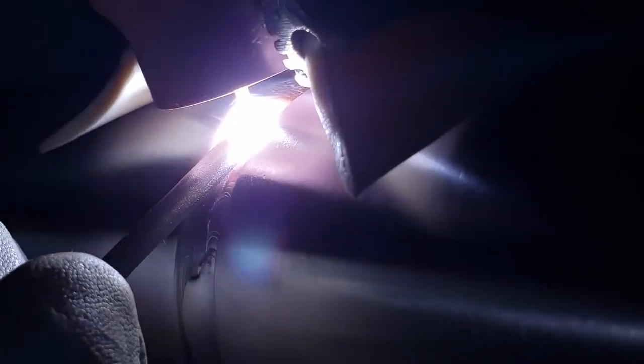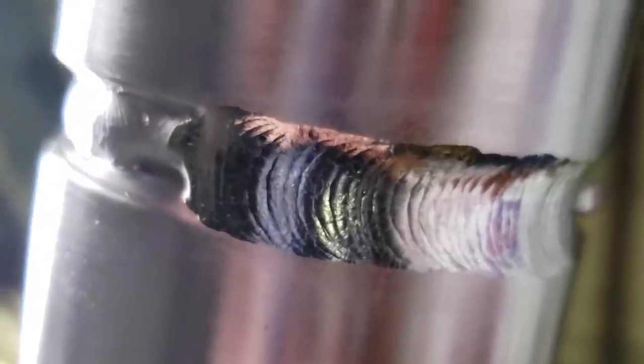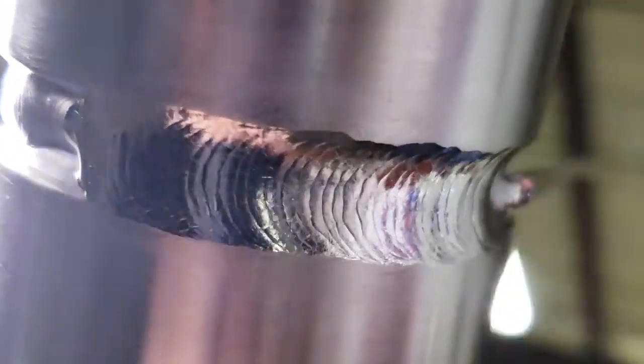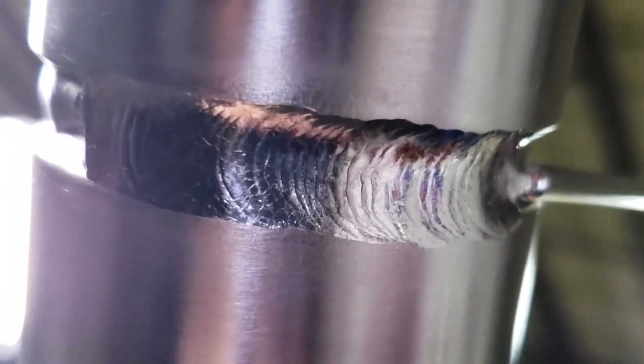But when it comes down to the nitty-gritty, the most basic form of welding titanium, the reason why you're given just a single size 8 ceramic cup and a size 12 is so the welder doing the training understands about protecting the deposited metal and the importance of the deposited metal. If you're able to do the welding using a single ceramic cup size 8 and size 12, and all the deposited metal comes out shiny and silver, then you're adequate enough to get away with using a more luxurious device such as a trailing shield.